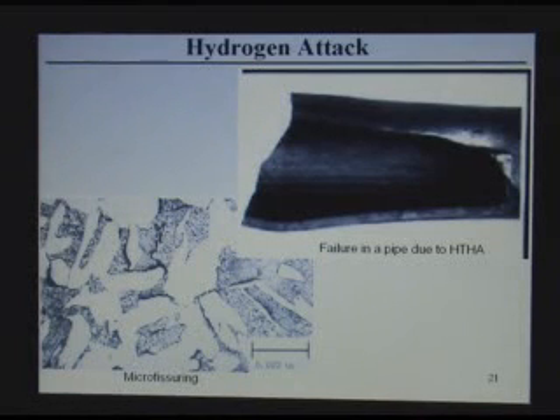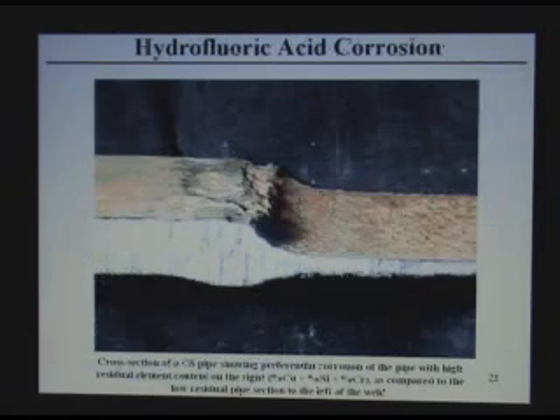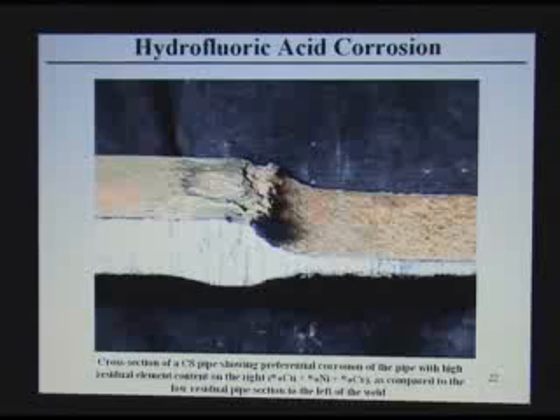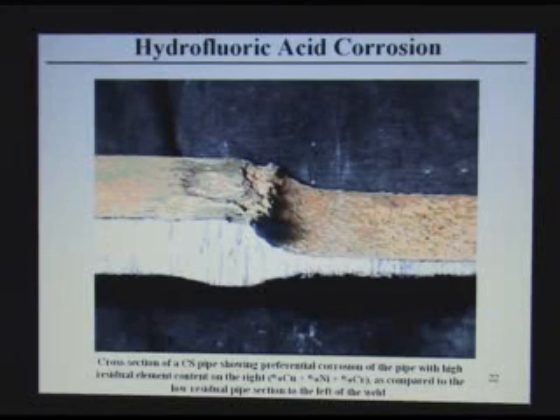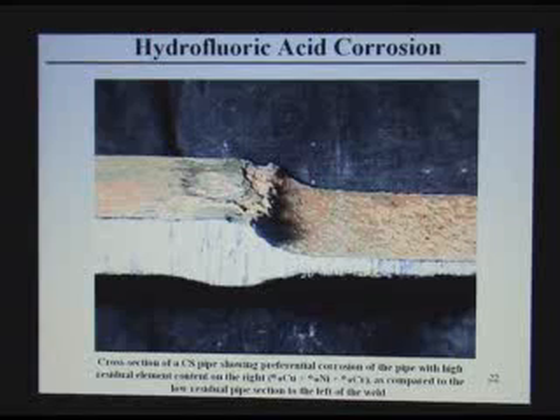This is, again, hydrogen attack. This is a regular structure, but you can see the fissures here from hydrogen attack, and eventually it shatters and breaks out. This is hydrofluoric acid corrosion. Hydrofluoric acid attacks certain metals vigorously, and if you have copper, nickel, chrome, it attacks. For instance, carbon steel has some of these alloys inside, so hydrofluoric acid attacked this part.